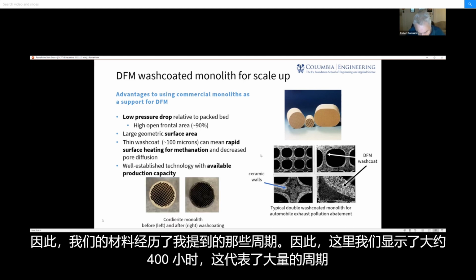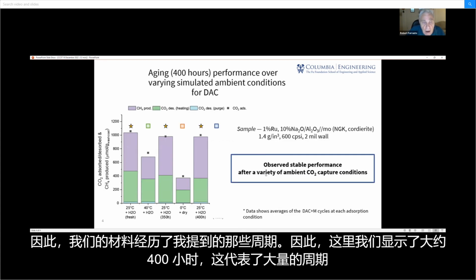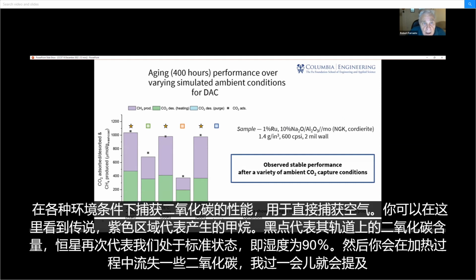So our materials then have gone through those cycles that I mentioned. Here we show approximately 400 hours, which represents a large number of cycles of performance of CO2 capture under a variety of ambient conditions for direct air capture. And you can see the legend here. The purple area represents the methane produced. The black dots represent the amount of CO2 absorbed, and the star again represents the fact that we're at our standard condition, which is effectively 90% humidity.